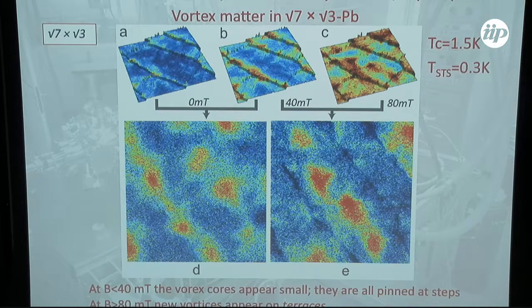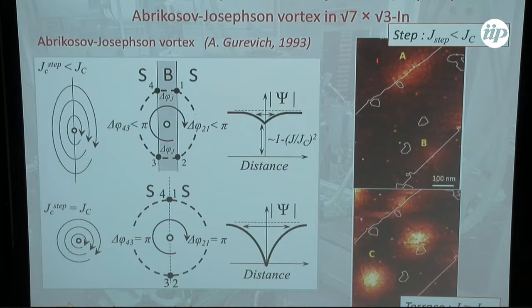Okay, so a similar result was obtained by our Japanese competitors who observed a similar situation in square root 7 by square root 3 indium, also a monolayer, also on silicon, it's indium. And you have exactly the same situation. On steps, you have these elongated vortices, and on terraces, you have round vortices. And these elongated vortices are just due to the fact that, while putting a vortex core, the singularity, just inside the junction, the system can accommodate a part of the phase gradient inside the junction, and so then it's easier to accommodate the rest outside, okay, with respect to the round vortex core, as we know in the Abrikosov case.